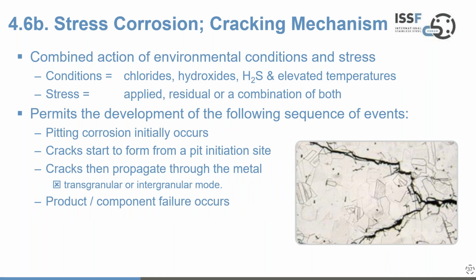And here's the mechanism. This is how it works. So you have this combined action of environmental conditions and stress. So the conditions are, as I said, an aggressive environment and elevated temperatures, and stress can be applied, residual or some combination of that. What happens then within the material is that initially the mechanism is pitting corrosion, and then cracks start to form from those pit initiation sites, and the cracks propagate through the metal or the alloy, and that can be in a transgranular approach across the grains or intergranular along the grain boundary, and then suddenly the product or component fails.